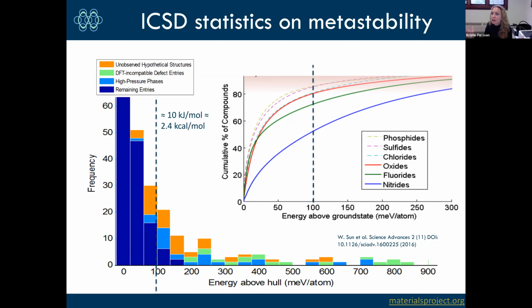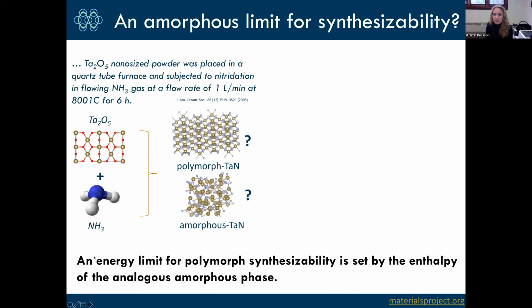And if we just put it at one number, we're not going to be able to catch a lot of promising nitrides. So we need to do a little bit better in terms of screening what can be made and what cannot be made, more sensitive to the chemistry. So we started thinking about, well, in synthesis of materials, what are you really competing with? Let's take an example. You want to make a particular tantalum nitride, and you're starting out from your precursors of tantalum oxide and ammonia. And you're wondering, can I make my particular target material, my particular polymorph, or am I just going to make amorphous junk?